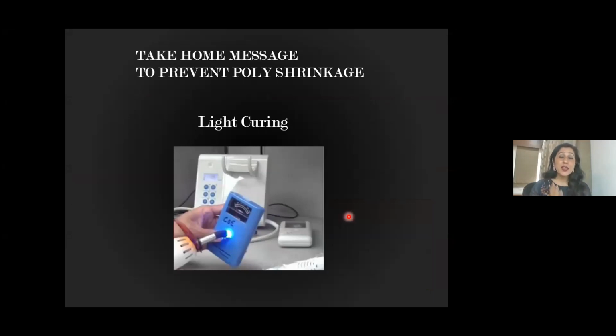Always remember to have some kind of checking device in your dental office, that is a radiometer. If you can buy a radiometer, that is really a very good investment, because then you know what intensity your light curing probes are producing. For LED, it is stated that the intensity should be between 1000 to 1200 milliwatts per centimeter square. And the wavelength of the light that is required: all the composites that are manufactured today have a photo initiator which gets activated in a range of 300 to 500 nanometers.